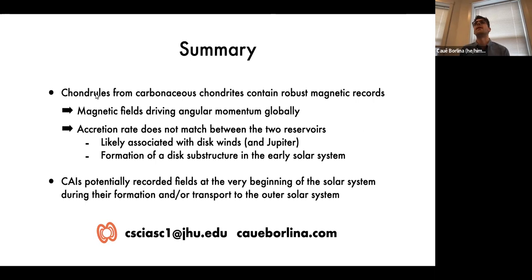Yeah, so a great question. When it comes to magnetic measurements, from the separation to the measurements, you have to make sure that everything you're using is non-magnetic. So we have this essentially dental tool that we demagnetize. And what I'm actually doing is physically scrubbing matrix out of the chondrule.